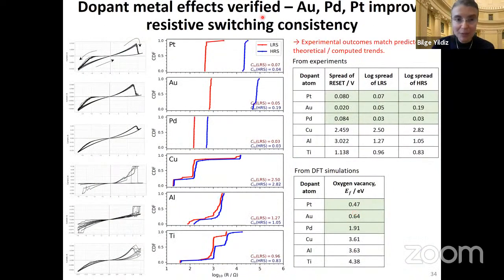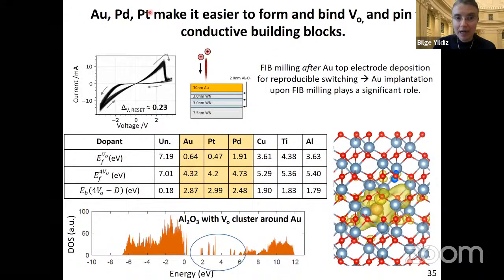And we could validate these computational predictions experimentally, where high electronegativity elements like palladium, gold, platinum, when implanted into alumina, show much better repeatability of the switching cycles, whereas with copper, excess aluminum, or titanium, we cannot improve this cycling stability, repeatability. That goes back to my argument that these high electronegativity metals make it easier to form oxygen vacancies by picking up the electron left behind from oxygen. And that gives rise to strong binding sites that are localized and allows us to use these building blocks to form conducting filaments or conducting networks.